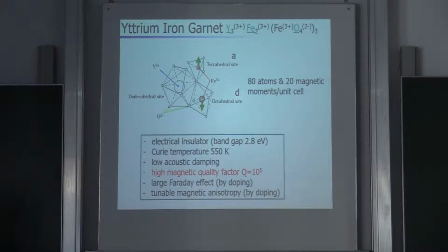Also interesting is the large Faraday effect, but this is achieved only by doping. And if you dope it, the magnetic quality goes down. One of the challenges for materials now is to find a YIG with a large optical coupling, but still high magnetic quality. People are really eager to have such a material. So if someone of you has ideas in this direction, that would be great.